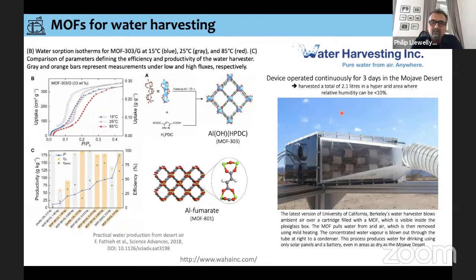Interestingly, there's been this work and publication, slightly controversial because the thermodynamics are maybe not as simple as we're seeing here. But this water harvesting company has been set up for the recovery of water under desert conditions. If we need water in the desert, then maybe it's possible to recover the water from quite arid air, and then once it's captured in the material, use mild heating to recover the condensed water. So the idea is to make drinking water using only solar panels as energy in quite dry areas. This is the setup that they have at the moment, or at least we can see on the internet. And they've just said that they've been able to harvest a few liters over 24 hours.